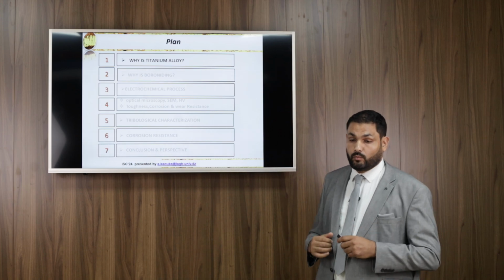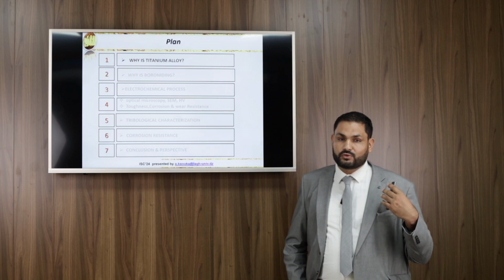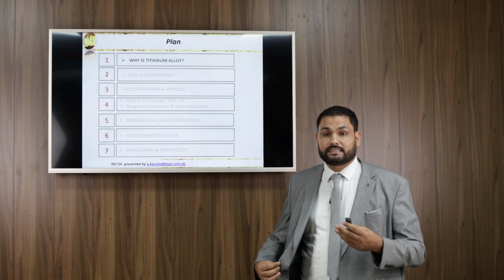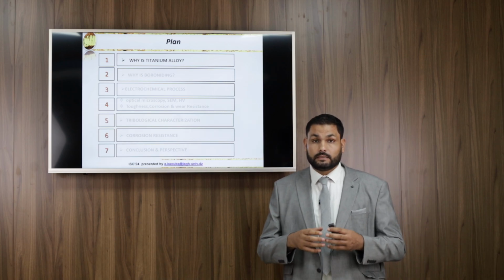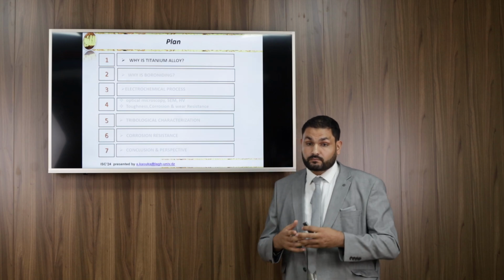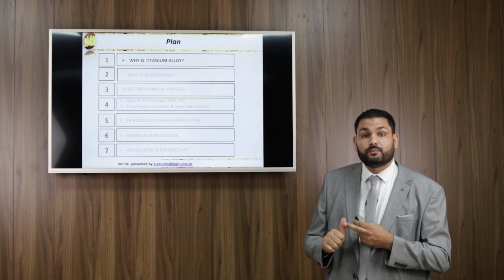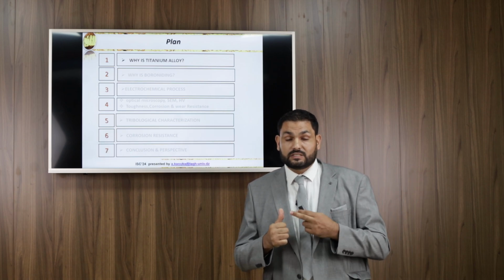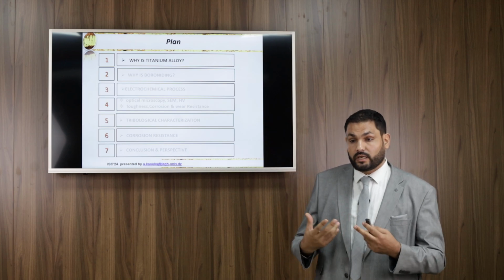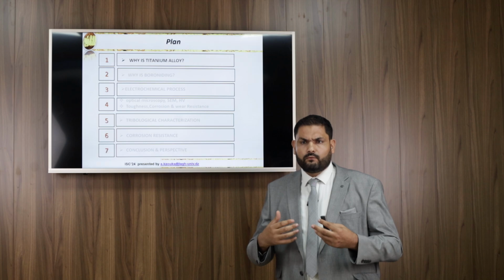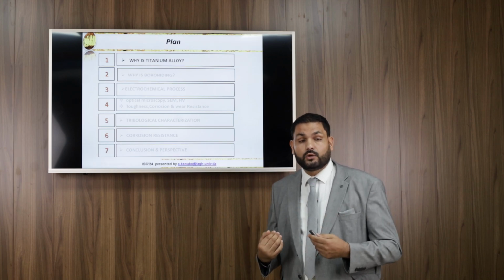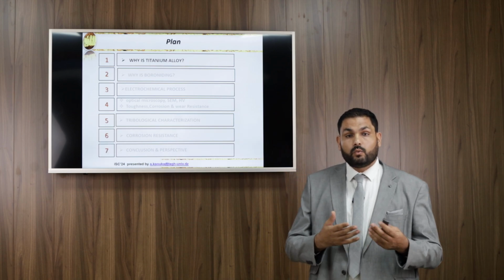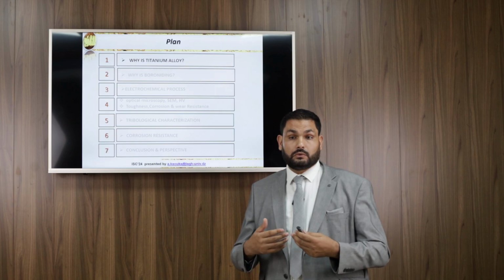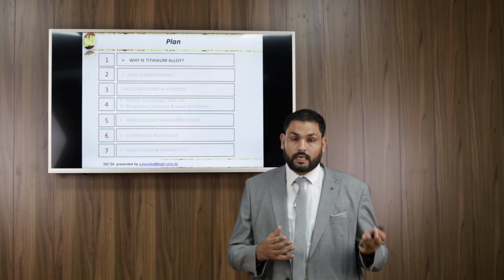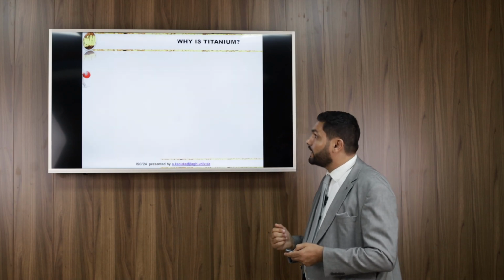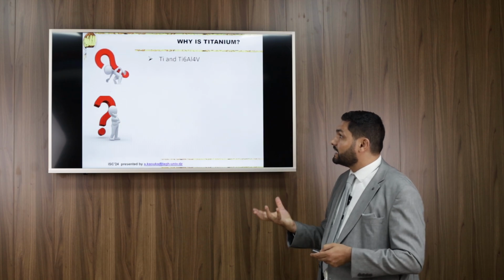So why did we choose titanium alloy? In our previous study, we used iron, cast iron, steel, and many other iron-based alloys. So in this study, we focus on titanium. First of all, because titanium is a promising material, especially in biomedical, as a biomaterial. It has relatively low density compared to iron. It's between iron and aluminum. So this is why we choose titanium alloy, titanium 6 aluminum 4 vanadium.